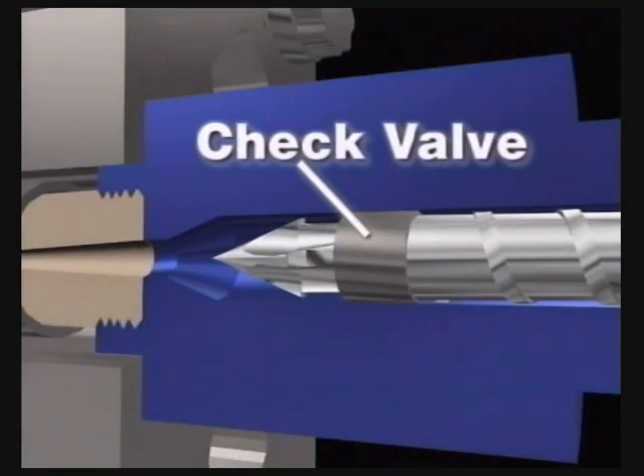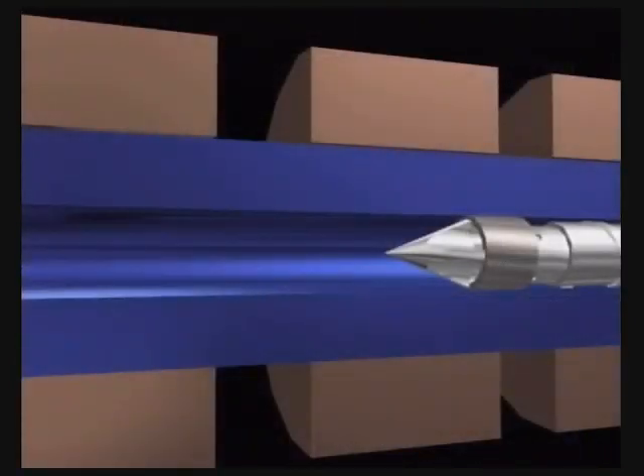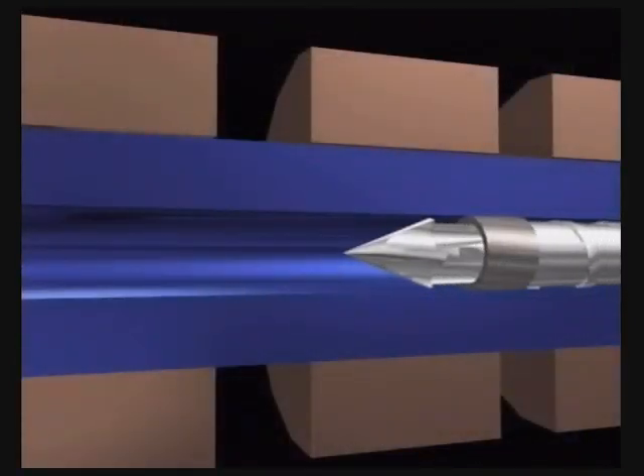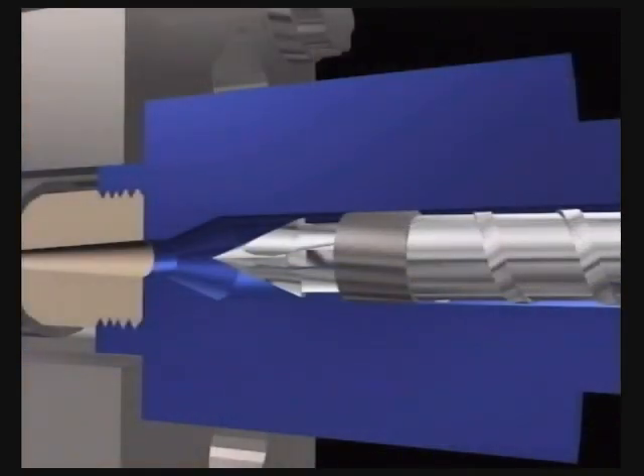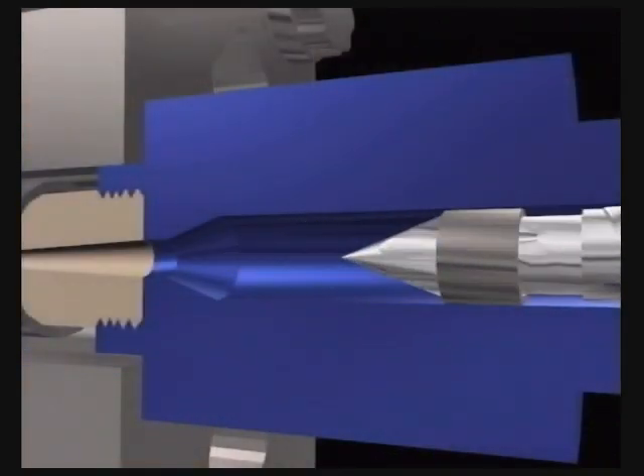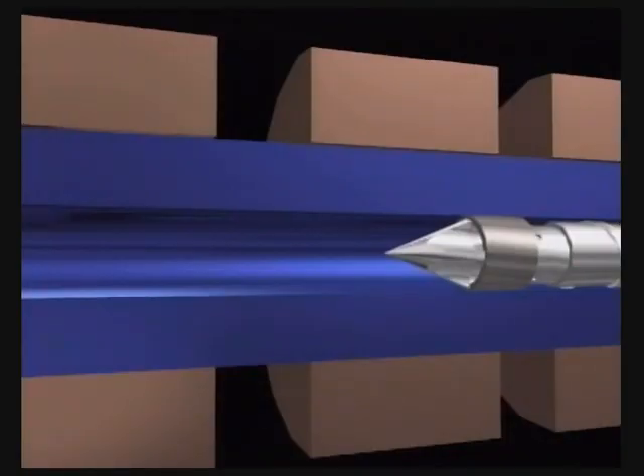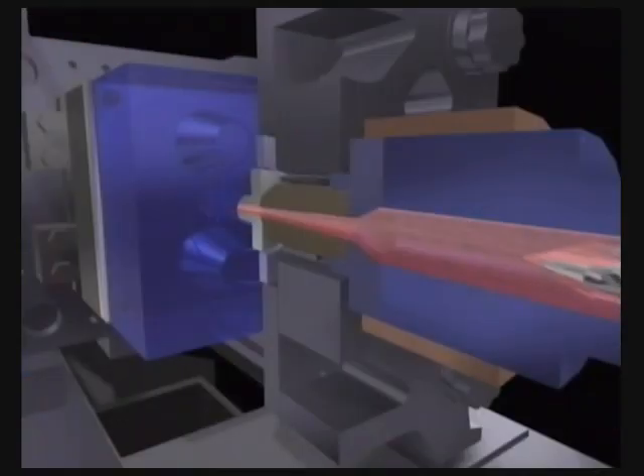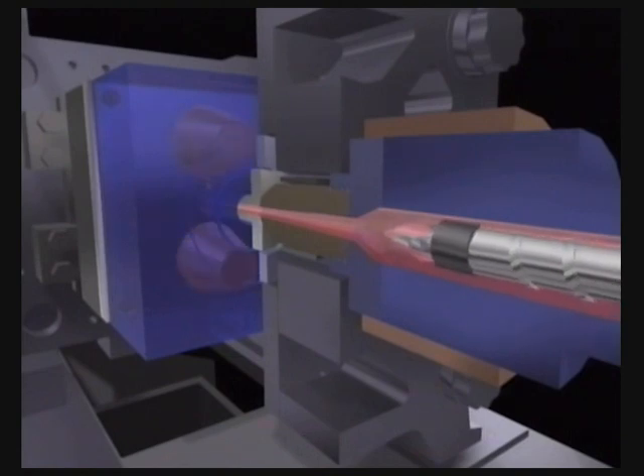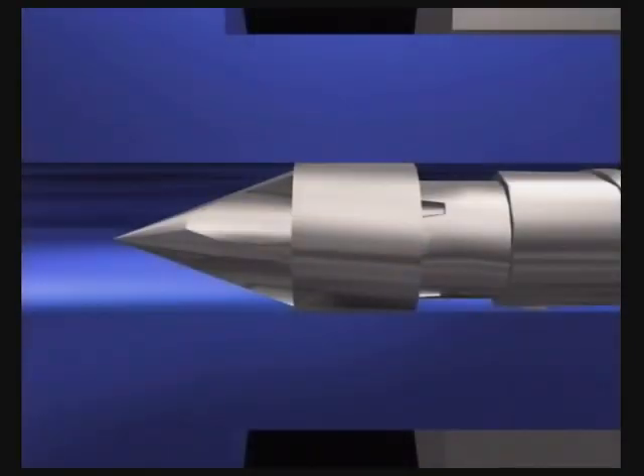Check valves are used on all machines to prevent material from flowing over the screw as it moves forward during the injection phase. The most common check valve used is the slip ring check valve. As the screw moves forward, the slider seats itself against the screw and prevents the melted plastic from flowing back. If the screw drifts forward through the melt cushion during packing, this is an indication that the check valve is not functioning properly. Material tends to collect and degrade in the check valve, causing poor seal-off.